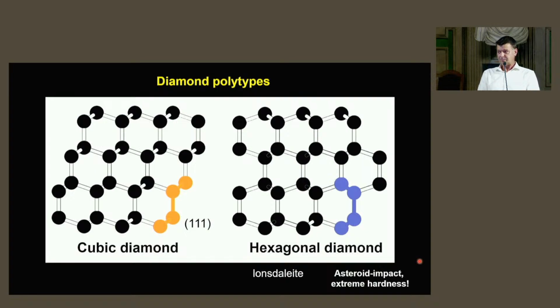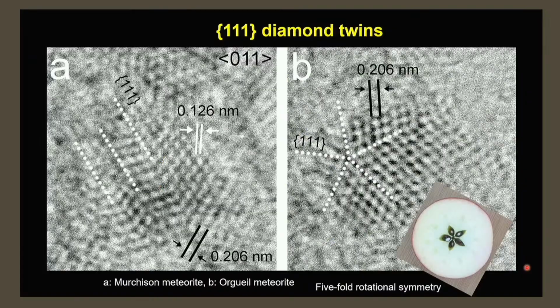And the scientists were intrigued by this material because since then they associated it with asteroid impact and used it for explanation. And here are some examples in the diamond nanocrystals. Actually, in the panel I am showing a polysynthetic twin. However, these twins, if you're talking about nanocrystals, could form even a beautiful star, and they show a 5-fold rotational symmetry, which more or less resembles the shape of this half-cut apple I showed even in the first slide.